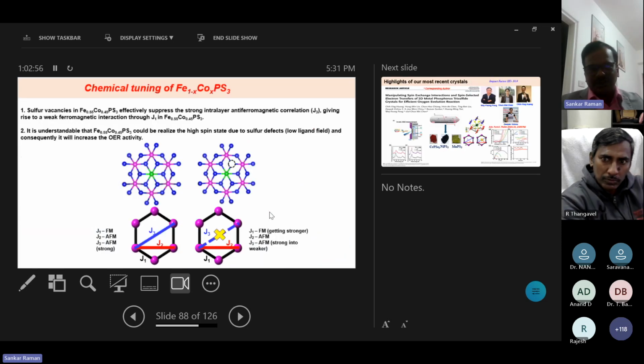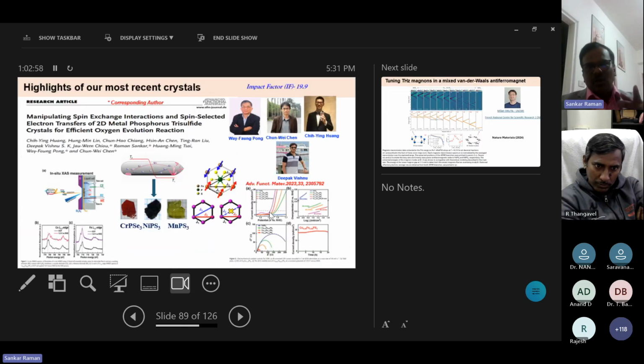Then I already discussed the sulfur vacancy. Once we create a sulfur vacancy, that material provides ferromagnetic nature at a low temperature, and also we dope the cobalt inside the iron site. We create a high spin nature. That high spin nature we used for OER and HER catalysis. This is very, very important.